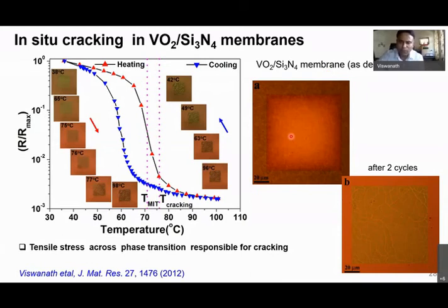But in terms of the membrane, is it silicon nitride or VO2? Sorry, I was confused. We have a 30 nanometer silicon nitride membrane on which VO2 is coated. Okay, but I still don't have an answer to your question. What is the critical stress for twinning and the stress required for cracking? That differentiation, in my opinion, is not done.